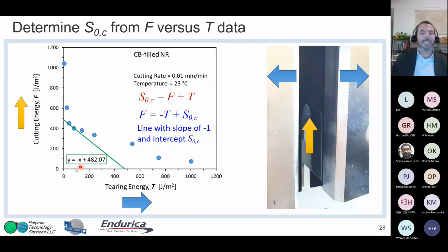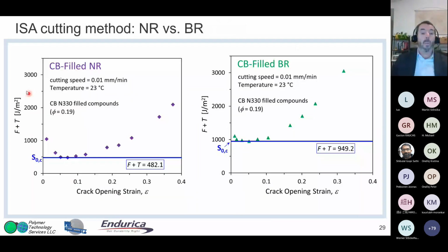And then one day I suddenly realized there's a lot easier way to understand this. If you add the F and the T together, you can plot that versus crack opening strain. So here's F plus T. We're going to plot it as a function of crack opening strain. And what you see is it's minimized. And where it's minimized is that same value, S0C here. And so here's carbon black filled natural rubber.